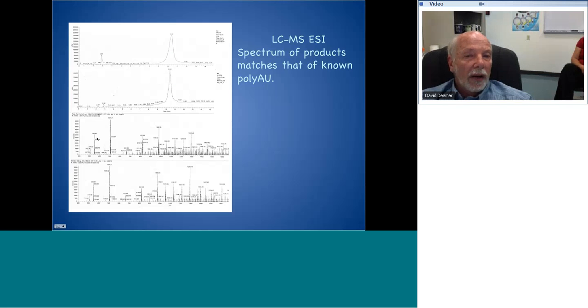And it's really quite extraordinary. The poly-AU is virtually indistinguishable from our product in terms of the kinds of peaks that we see in here. And when you analyze the distances between these peaks, they fit what you would expect of a double-stranded material of varying duplex chain length. We have a lot more to do with this. We're consulting experts with mass spec, which we are not yet. We're trying to get a little more expertise, but that's also our next year's work, is to really get at this with MALDI and electrospray mass spec, which we have here.